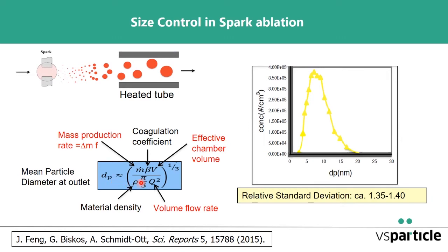And obviously, it's the mass production rate, the m dot, that you can adjust in the VS Particle unit. That is important. Obviously, it's also the flow rate, which is also adjustable. And it's the effective chamber volume. Now, in the case of the hollow electrodes, the effective chamber volume after the particles have been ablated is simply the volume of that hollow electrode. So that's a very small volume, and that would be a way of producing rather small particles.